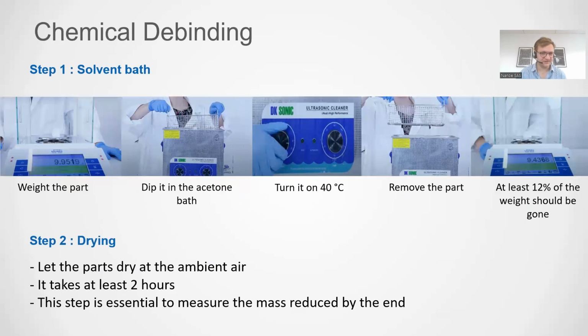The chemical debinding is very simple, with any vessel where you can put acetone. We use ultrasonic cleaners, but you could use something different. And we put the part in small baskets so that you can dip them in acetone and check that you actually have some loss of weight during this debinding step. Very straightforward. It takes a few hours, sometimes we leave the part overnight if they are really big, but that's again a very straightforward process.